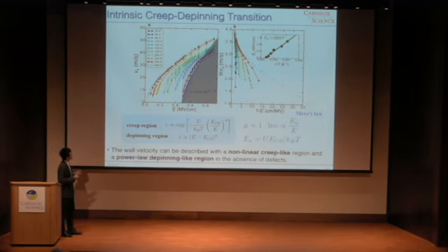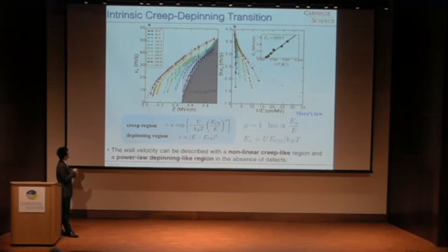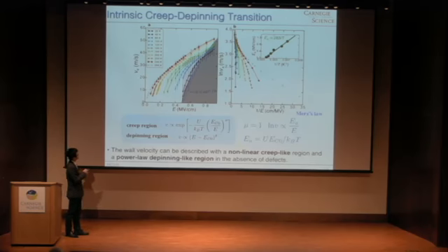So this slide summarizes the results of hundreds of simulations. It shows the velocity as a function of electric field. Very interestingly, it has 2 regions. Here, at the low field regime, we can see that the domain wall velocity has very significant temperature dependence. But here, the lines start to overlap with each other, which is a signature of the depinning region.